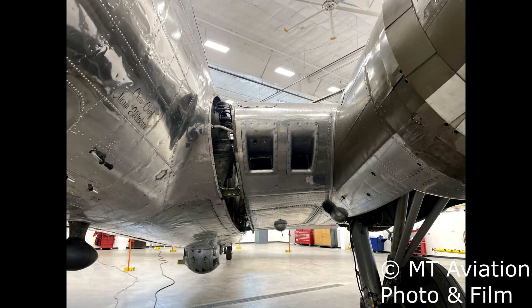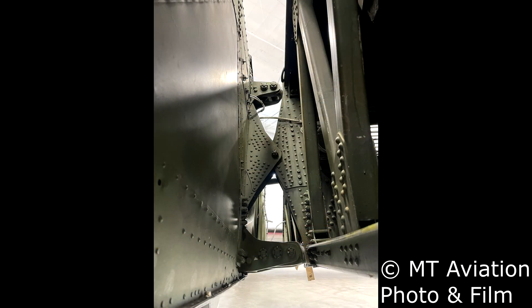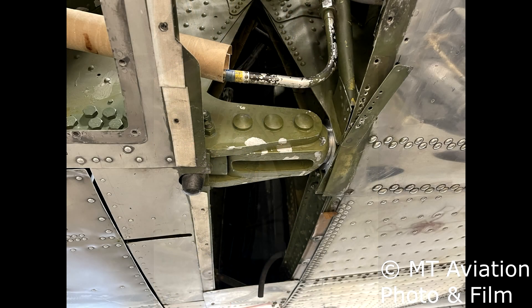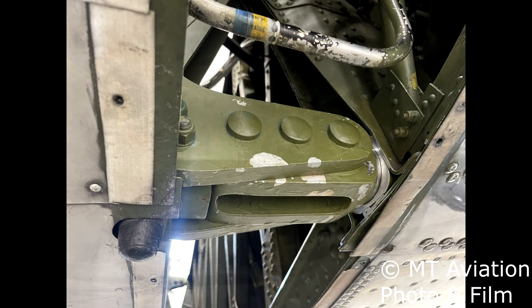To take a look at the procedure, we dive into the wing root of the B-17, where the wing is connected to the fuselage. Although each wing has a forward and aft web spar, each having two primary mounts on it, the inspection is only concerned with the lower forward mounting areas of each wing. The affected area for the inspection is the inboard-most bolt hole on the wing terminal, which is where Aluminum Overcast was discovered to have had a crack. The terminal, in simple design terms, is more or less a fork with two tabs which three pins run through connecting the wing to the fuselage.